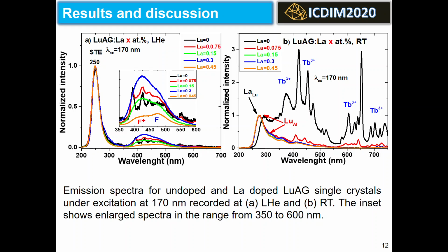Interestingly, the position of the emission centered at 250 nanometers is independent of the crystal composition, and it is completely quenched at room temperature. Hence, this luminescence might be connected to the radiative relaxation of the self-trapped excitons. Emissions at 415 and 475 nanometers belong to F+ and F centers.